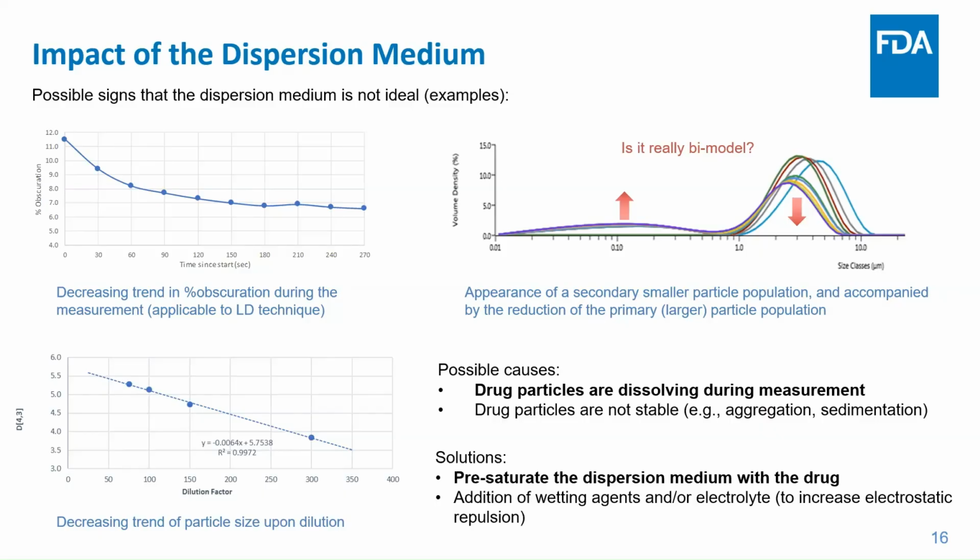And in this case, we understood, and this is brinzolamide and also Lotemax, it's the same. Those two products share a very similar situation, like what's shown on this slide, that both loteprednol suspension and the brinzolamide suspension have this problem of potentially drug dissolving during the measurement. So you need to really saturate the drug solution and also choose the appropriate setting, medium, etc.